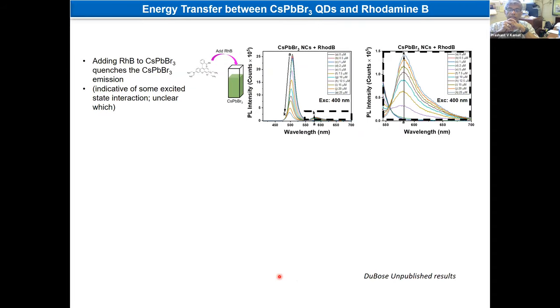So what we are just now looking into is this rhodamine dye. It can interact with the cesium lead bromide. So in this case, what you can see here, you increase the rhodamine dye and the emission of cesium lead bromide quenches, and the emission, again, is not as high because of the quantum yield of emission, but if you magnify this one here, you can see the emission of rhodamine B goes up. And this is excited at 400 nanometers, where rhodamine B does not absorb.